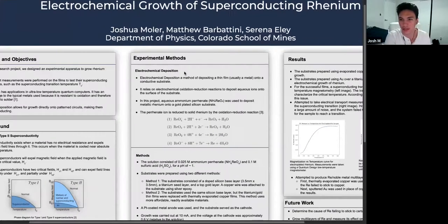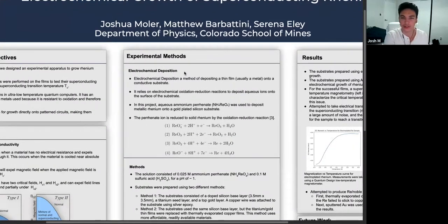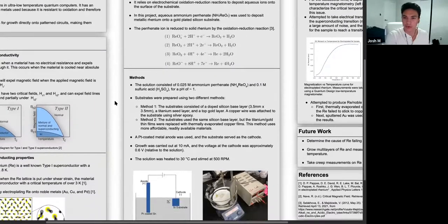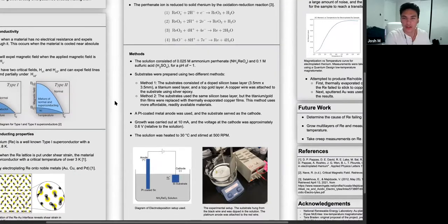So our experimental apparatus here was pretty simple. We're doing electrochemical deposition, which involves oxidation reduction reactions, which take aqueous ions and essentially just deposit them onto a conductive surface that is dipped into the bowl of chemicals. For our setup, we used 0.025 molar ammonium perrhenate, which contains a rhenium ion when it is aqueous. That allowed us to basically reduce the rhenium down to where it deposited onto our substrate in metallic form. We also kept the entire apparatus at about 30 degrees Celsius and stirred it at 500 RPM.